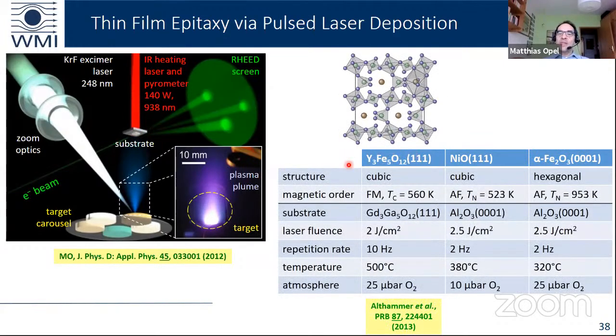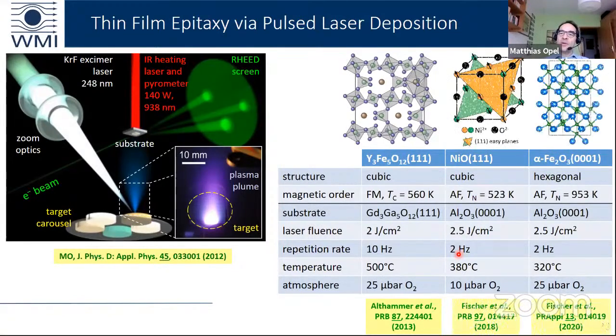So we were growing the yttrium iron garnet. The growth parameters are given here. We were also growing antiferromagnets like nickel oxide and hematite. And the crystallographic structure is given here. And the details of the growth conditions are given here. All the work is published in these two papers by Johanna Fischer et al. We found an epitaxially oriented growth of all our samples and no secondary phases.